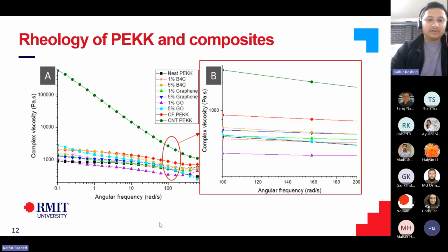So these are the rheology results. First, I performed a strain amplitude sweep test to determine the linear viscoelastic region, and then I applied shear within the elastic region to determine the complex viscosity.